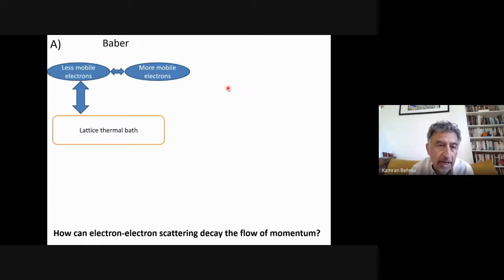So, of course, people knew this, and they had two different ideas. One idea, which was explicitly formulated by Baber, is that if you have two kinds of electrons, you can have momentum exchange between these two reservoirs of electrons. Imagine now that one group of electrons is more strongly coupled to the thermal bath. In that case, you have these two reservoirs exchanging momentum. This exchange of momentum between these two groups of electrons will create a kind of bottleneck. Even if the ultimate loss of momentum is here, since this canal is much wider than this one, you are going to see T squared in this way. So it's a very indirect way, but why not? That was what he proposed, in particular in the case of palladium.